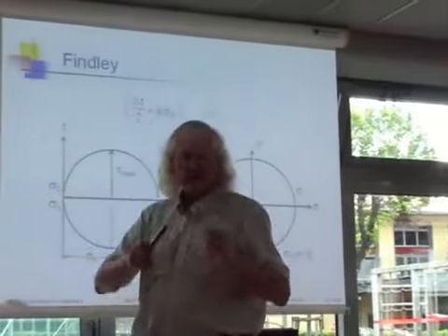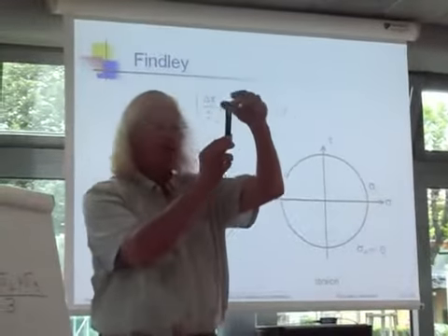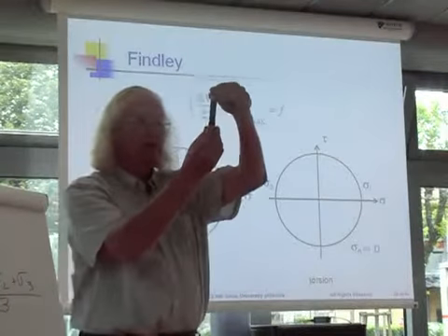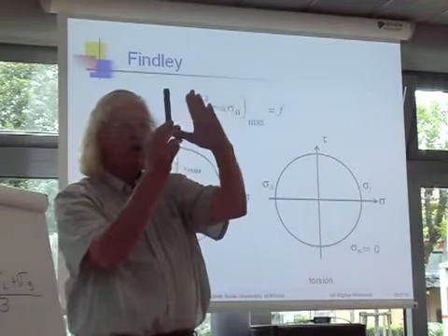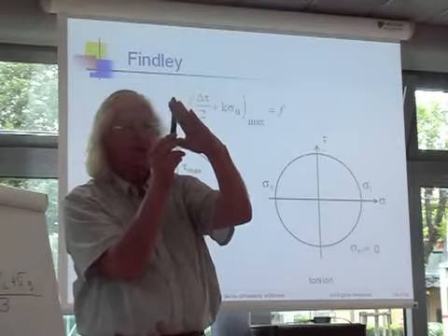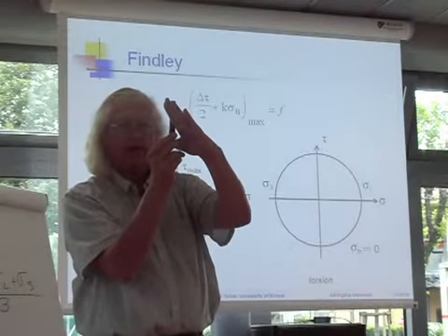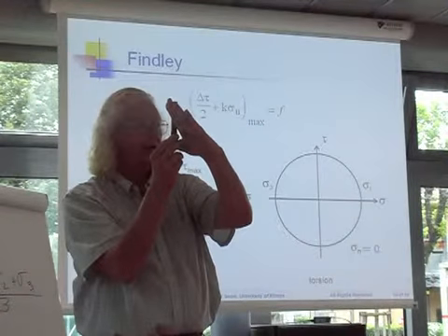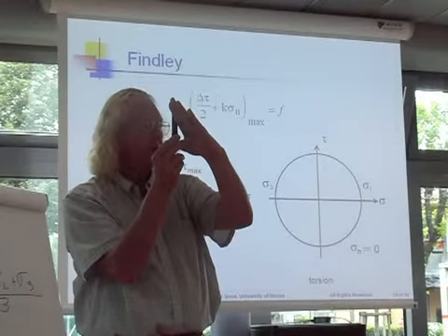What is that difference? Well, there's more to the Mohr circle for tension and torsion. Right? So I have the bar, and I'm going to load this in tension. And of course, we know that maybe a fatigue crack will form on a plane which is oriented 45 degrees to the axis. And let's look at what happens on this plane.